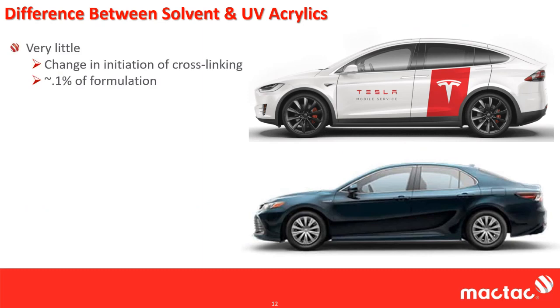and you'll start to see why. So when I say what's the difference between solvent and UV acrylic, very little. There is very little change or differences. The only thing is a change in the initiation or the cross-linking. In most adhesives, that accounts for maybe 0.1% of the formula. The monomers that go into making the backbone of the acrylic adhesive are the same in a lot of cases.